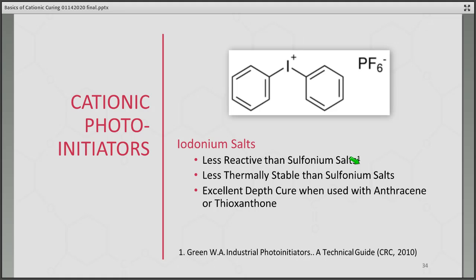Another class of cationic photoinitiators that are commonly used is iodonium salts. And we have the structure here. Instead of sulfur, we now have iodonium. These tend to be less reactive than sulfonium salts in lab tests. They're also less thermally stable than sulfonium salts. However, they give excellent depth cure when used with either anthracene or thioxanthone systems. So they're a good tool to have in your tool chest when you're formulating. Again, not as commonly used as sulfonium, but they're still used quite a bit out there, and they're very useful.